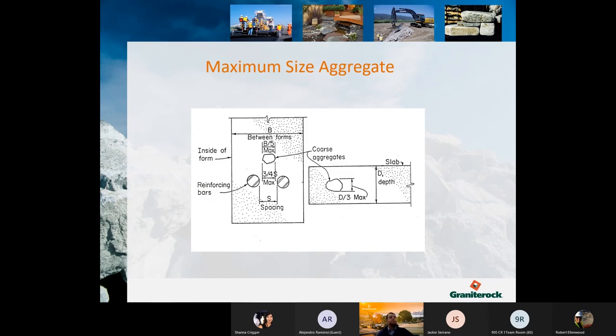One thing to note also with aggregate size, it's not just the economy of cement use, but also application in the field. So here's a small little detail to show why that matters. If you have tight rebar, you really have to think about the maximum size of your aggregate. You want it to be smaller than how far the rebar is spaced to allow the concrete to flow easily.